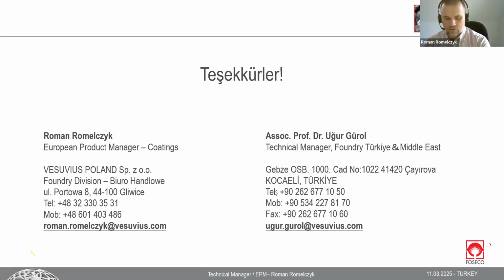It's not that problematic to use both of them. The zircon one has a 30 micron grain size and smaller, and corundum as well. It's more neutral from the chemical side. In the past, for main parts of stone crushing machines, we used a zircon one and a manganese top coat. It improves the casting results, but does not fully eliminate the penetration problem.